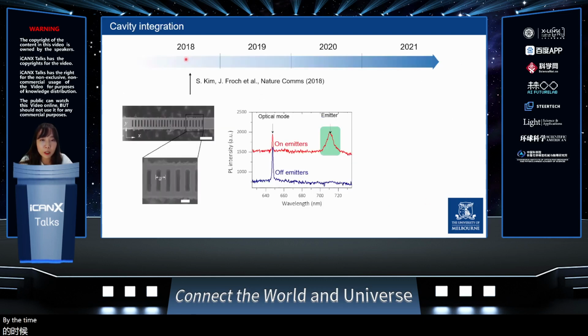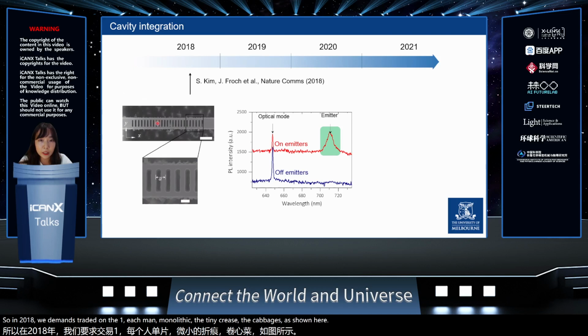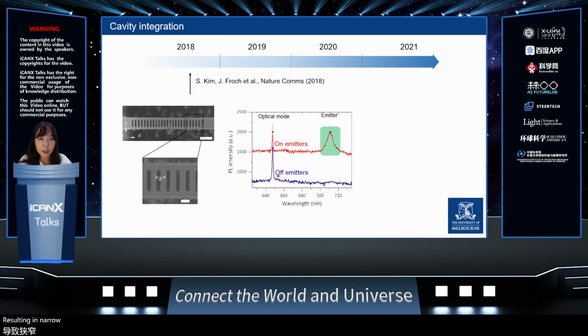By the time we started this research, the wavelengths of quantum emitters were still random. So in 2018, we demonstrated the first hBN monolithic photonic crystal cavities, as shown here. These are SEM images showing one-dimensional photonic crystal cavities made of hBN only. The optical mode has a Q factor of up to 2000, resulting in a narrow linewidth in the spectrum. And hBN emitters typically have a broad linewidth at room temperature, as shown in this green shaded area.